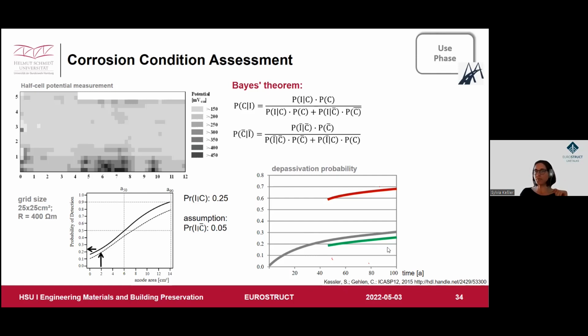So now look here at the spots. Now we have a very high corrosion probability, or a very high indication, I would say. Then we could derive that we have a depassivation probability of above 60%. Now you need to be really concerned. The 60%, I think this is still a lot.